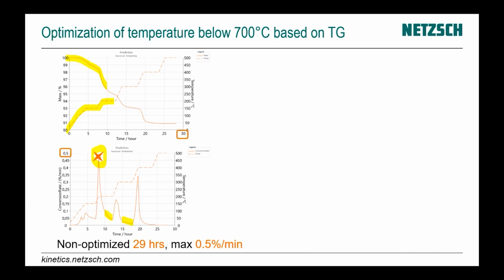Why do we lose quality at this point? Because during the very intensive decomposition of polymer, we have production of gas because of decomposition. And if this happens very intensively, then usually for the pressed ceramics, there is no time for this gas to go out from our ceramics. And then this gas can destroy or damage the structure of our ceramics. So we must avoid the points with very intensive gas production, with very intensive decomposition process.